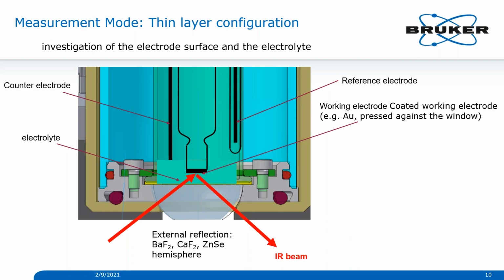And in this setup, we use an external reflection setup with a barium fluoride, calcium fluoride, or zinc selenide window. As you can see here, light from the spectrometer goes through the hemisphere and then through the electrolyte, reflecting from the surface of the working electrode, goes through the electrolyte again, and then goes to the detector. As you can see, most of the signal comes from the electrolyte, and a part of it is also from the surface, but mostly from the electrolyte.